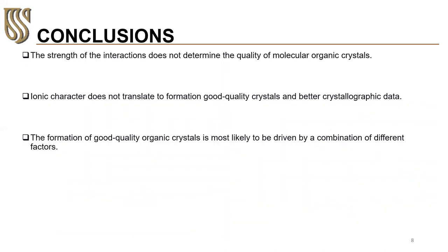In conclusion, the study has shown that the strength of interaction does not determine the quality of organic crystal obtained. The ionic character of organic crystal does not translate to the formation of good quality crystals and better crystallography data. This might be true for inorganic crystals with charged ions, but certainly not in molecular organic crystals. The formation of good quality organic crystal is most likely to be driven by a combination of different factors.